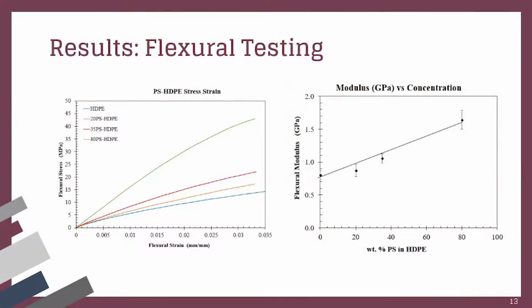In our results, we concluded that the higher the percentage of polystyrene, the stiffer it is, which is shown by the modulus, which is a slope from the first graph, and is a consistent increase.